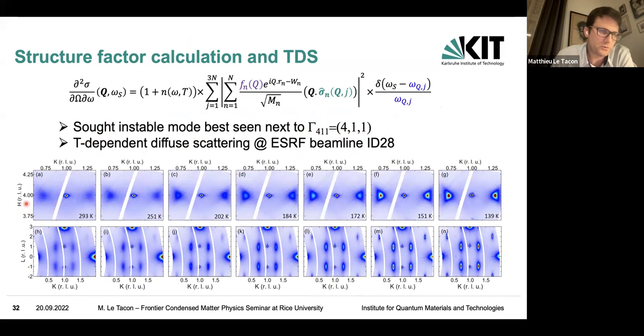So here I show you some cuts. This is the 411 Bragg reflection, and this is the HK plane, and this is the KL cut. At room temperature, we really nicely see a very beautiful diffuse scattering signal here. It's a fantastic detector; there's basically no background. And you see that already at room temperature, you have a nice diffuse peak.